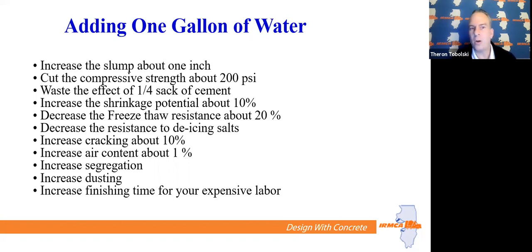It increases the air content by 1%, right? Every yard of concrete that will be seeing freezing and thawing has an air percentage range that it needs to be in, typically 5 to 8% to be freeze-thaw durable. So every time you add water to a yard of concrete, you increase the air. And when you increase the air, you actually decrease the strength, which then hurts the durability. So you kind of got a 2-for-1 whammy against your concrete when you're adding water.